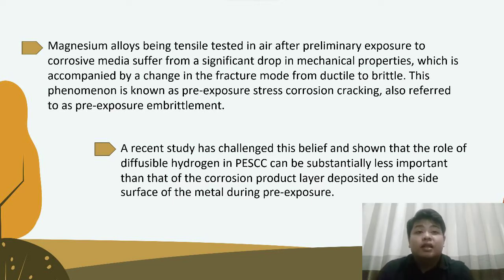For example, the widespread belief that hydrogen plays a key role in the mechanism of SCC is primarily based on the observed similarity between the features of PESCC and hydrogen embrittlement or HE in other metallic materials. It is established that the degree of PESCC in many magnesium alloys increases with decreasing strain rate and increasing time of pre-exposure in various corrosion solutions. Longer pre-exposure was found to cause more significant corrosion damage and a larger brittle-like area on the peripheral parts of the fracture surface, accompanied by an increase in hydrogen concentration in the test specimen.